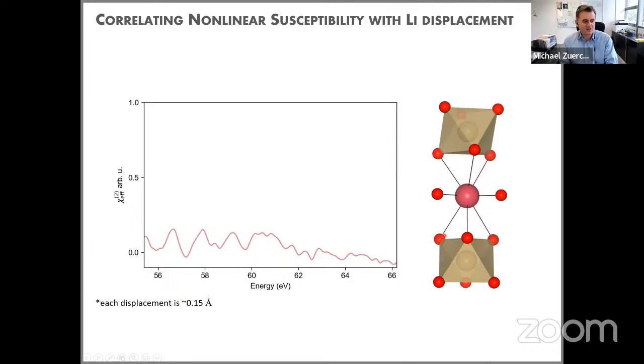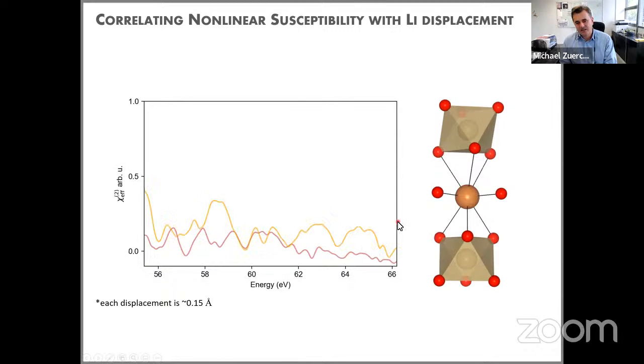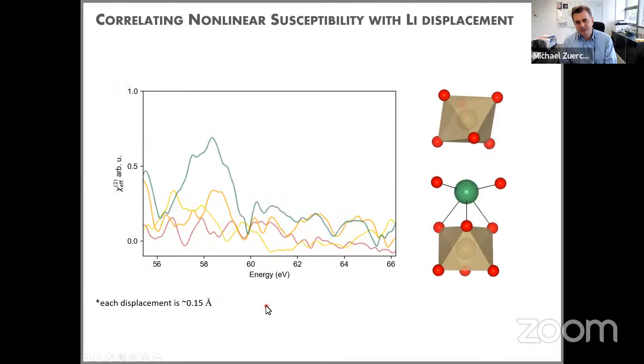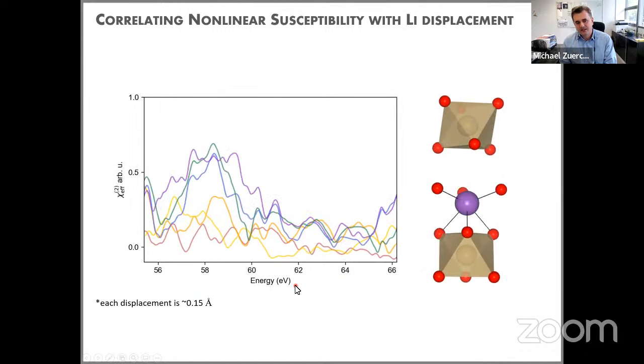So almost center symmetry, right? In this case, we expect next to no second harmonic, within, say, the numerical noise. Then if we start displacing the lithium along the bond, and each of those steps is about 0.15 angstrom, we see that the more we displace, the more second harmonic we get.